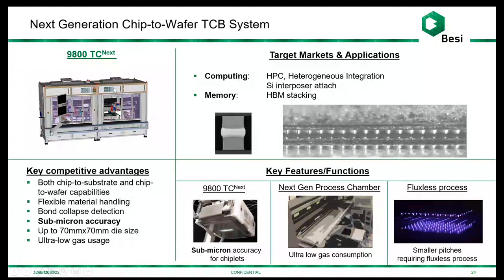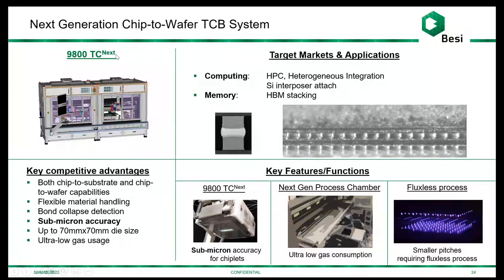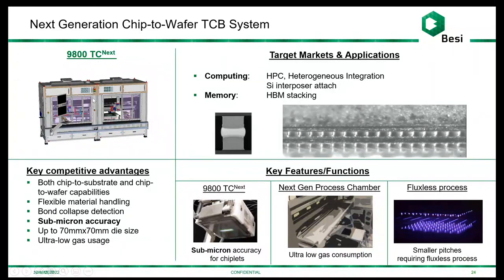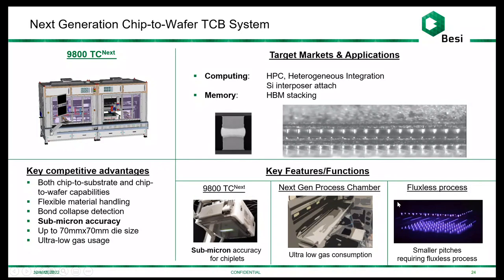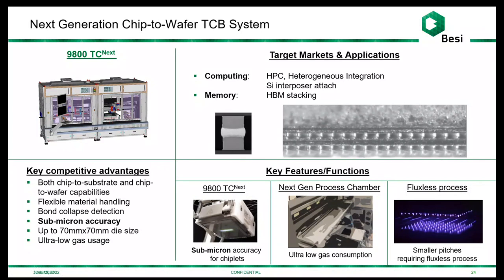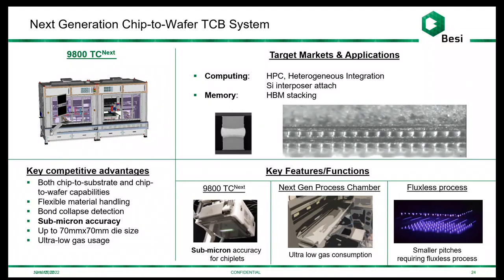For these applications, we're introducing a new platform, the 9800 TC Next, which is a chip to wafer thermocompression bonding system with about half a micron placement accuracy, so still very fine accuracy, with controlled atmosphere environment and even fluxless capability. And this is really targeted at chiplets that don't require hybrid necessarily, but either require the assembly of a hybrid chiplet to the substrate or just two fine pitch chiplets together on the substrate. So this is coming to market in Q1.